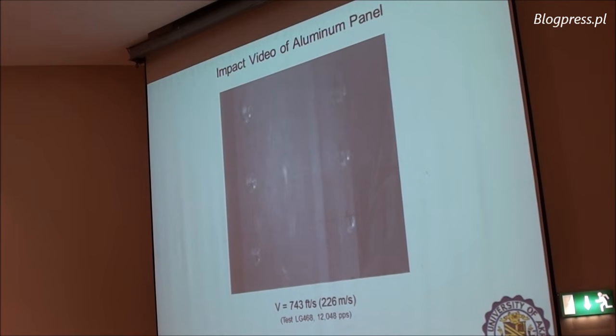test itself. This is an interesting test because it will show how aluminum, the original material, will behave under the gelatin, which is the so-called artificial bird. Well, here you are, it breaks through, and not only does it break through, but it rips open a huge hole. So aluminum, as a standard material, is very dangerous because yes, it is elastic plastic, but if it breaks, it can open a significant hole in the engine, and therefore those cracks are not arrested.